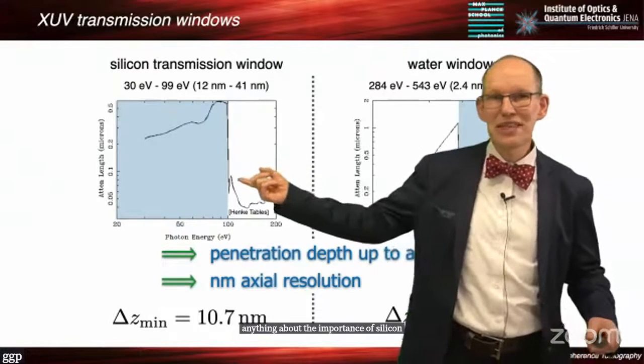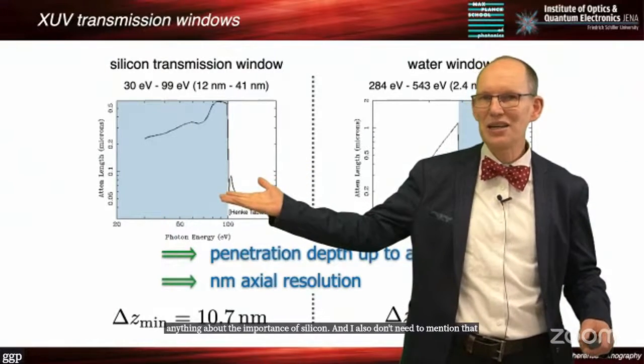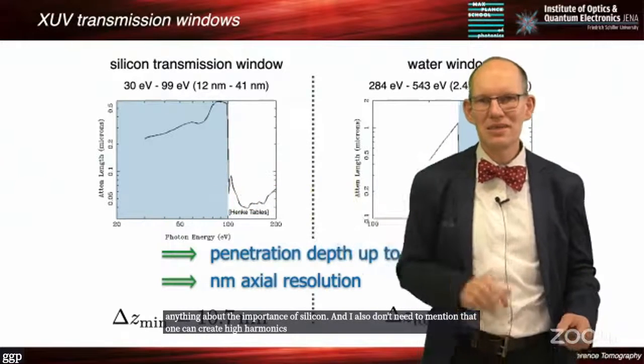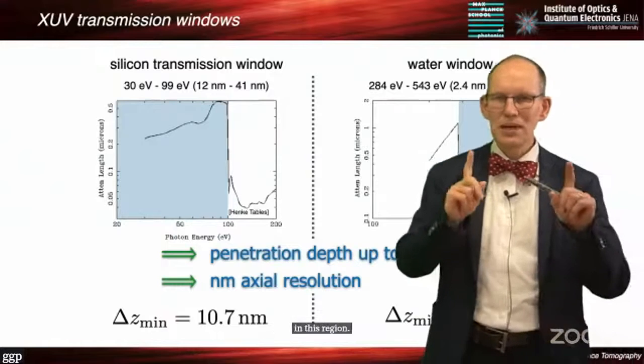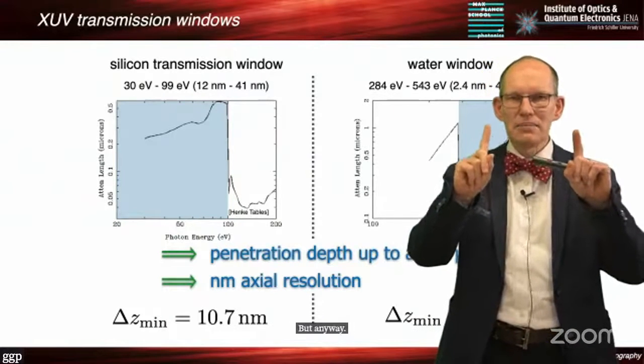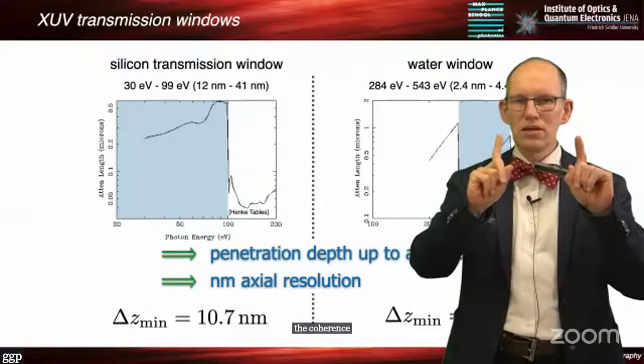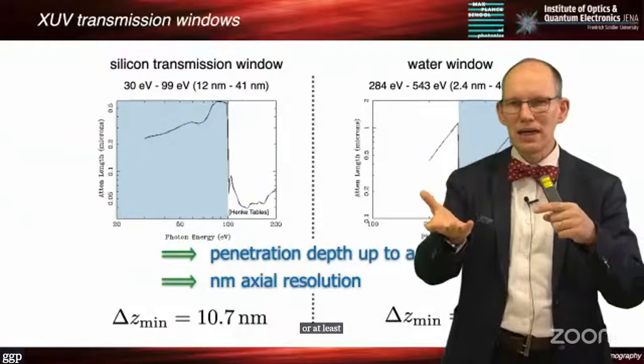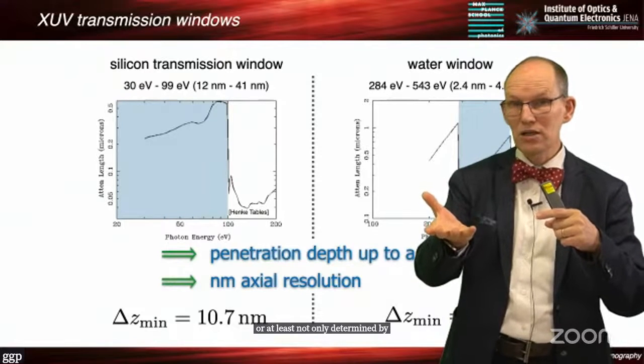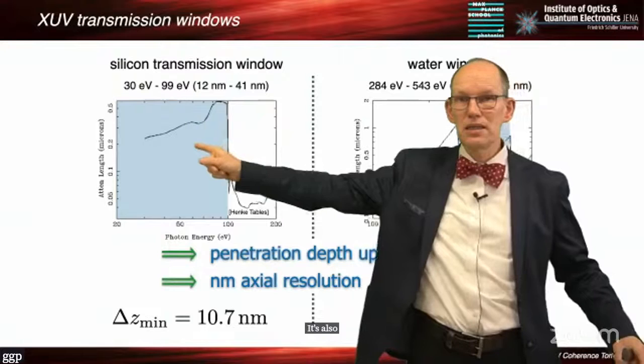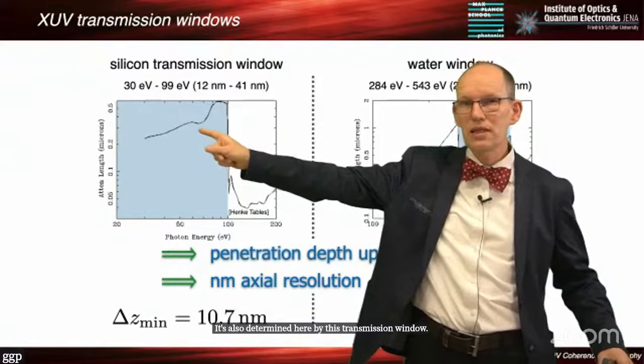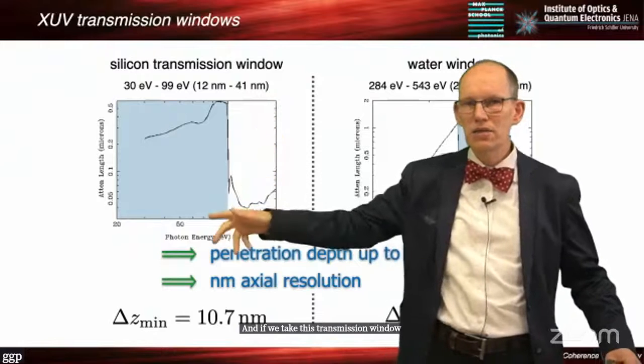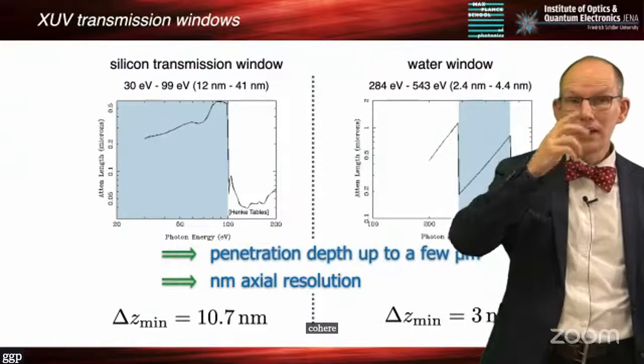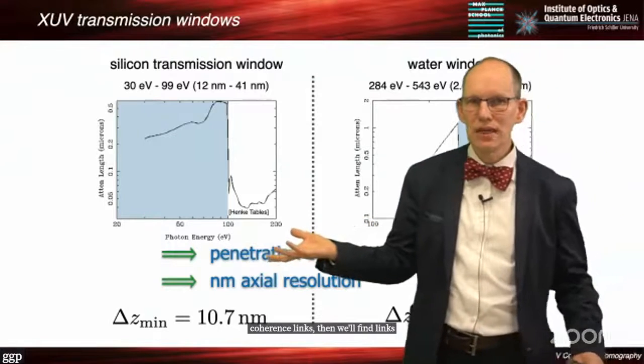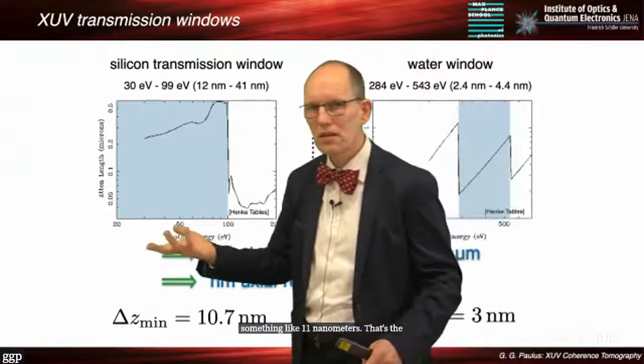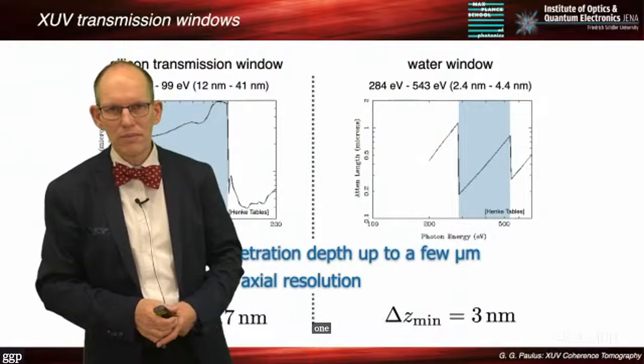I don't need to say anything about the importance of silicon. And I also don't need to mention that one can create high harmonics particularly nicely in this region. But anyway, the coherence length is now no longer, or at least not only, determined by the high harmonic spectrum, it's also determined by this transmission window. If we take this transmission window and calculate the corresponding coherence lengths, we find something like 11 nanometers. That's the resolution, the limit one can achieve for silicon.